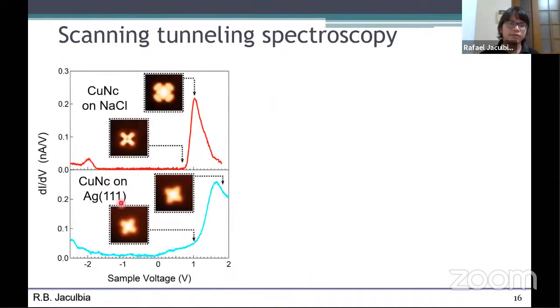Scanning tunneling spectroscopy allows us to measure the electronic states of the molecule by measuring the change in current as we change the bias voltage between the tip and the substrate. So here are two scanning tunneling spectroscopy spectra. When the molecule is on silver, we were only able to find one peak. Whereas when the molecule is on NaCl, we found two peaks, one on the positive side and one on the negative side. Based on calculations, this one can be identified as the LUMO, the lowest unoccupied molecular orbital, and this is the HOMO of the molecule.